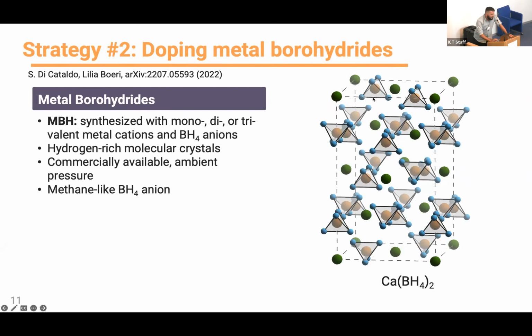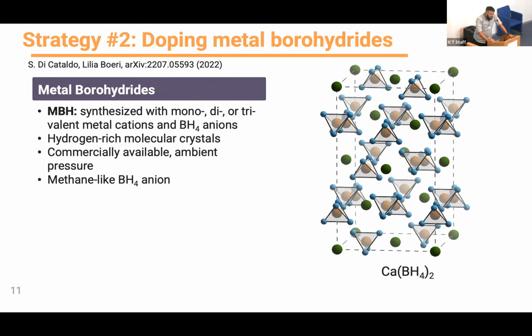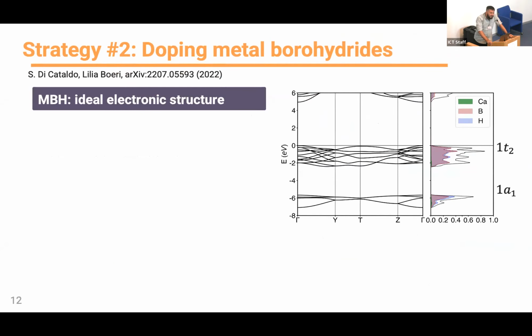Metal boron hydrides are synthesized using a mono-, di-, or trivalent metal cation, which in the structure that I'm showing here on the right is calcium, and BH4 anions. The way this structure is formed is essentially that there is a charge transfer from calcium to the BH4 anion, which is isostructural and isoelectronic to methane. Now, again, these structures are insulators, but the good thing is that they are commercially available. You can buy them relatively easily. And so let's look at their electronic structure.